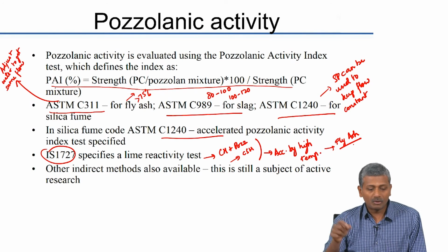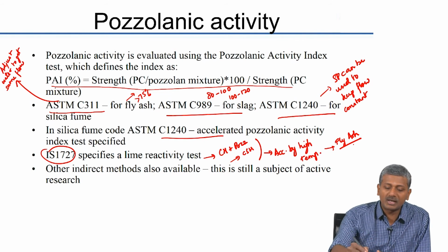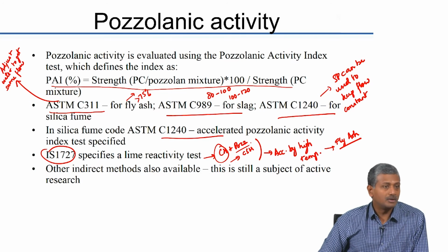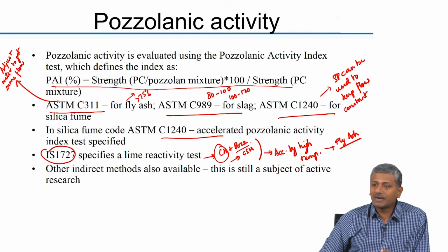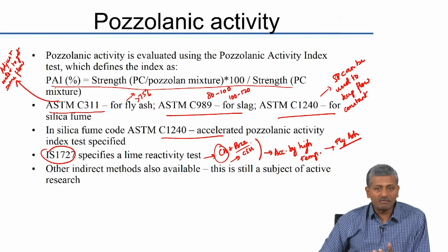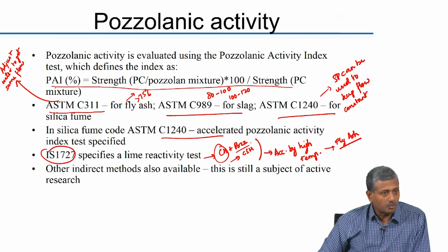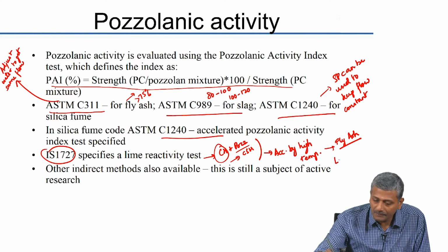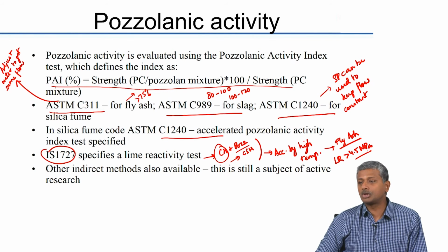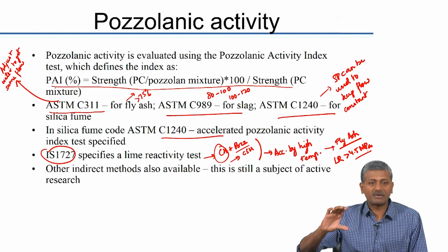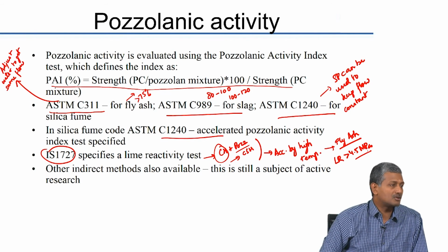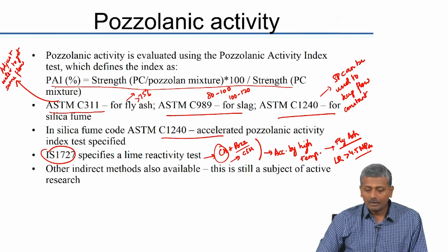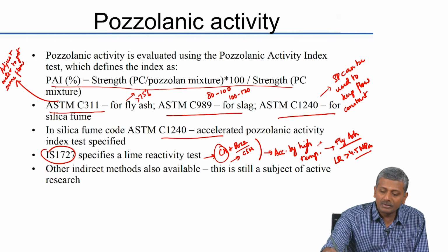Okay. If you look at that standard, it will tell you exactly how much lime you need, how much pozzolan you need, and so on. So, for fly ash to be qualified as a good pozzolan, the lime reactivity should be greater than 4.5 megapascal. Here the units are just the strength of the cube. When you test the cubes of fly ash, they should at least break at a strength of greater than 4.5 megapascals. Again, because of the high temperature, I think the entire test gets done in 8 days.